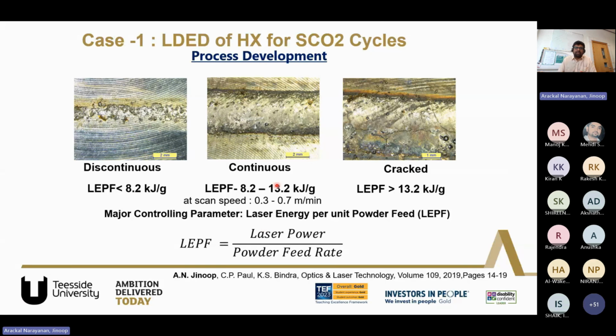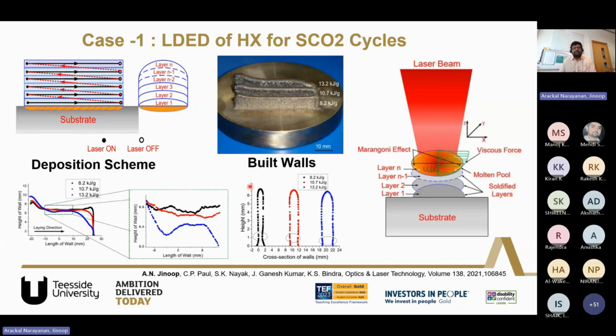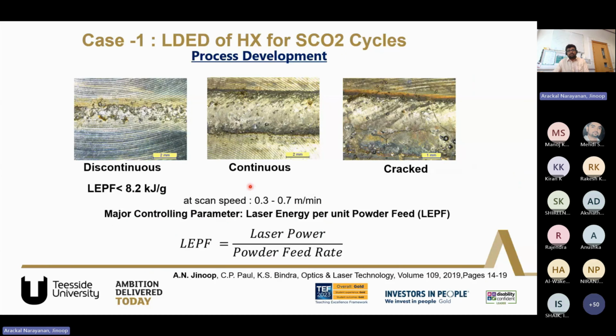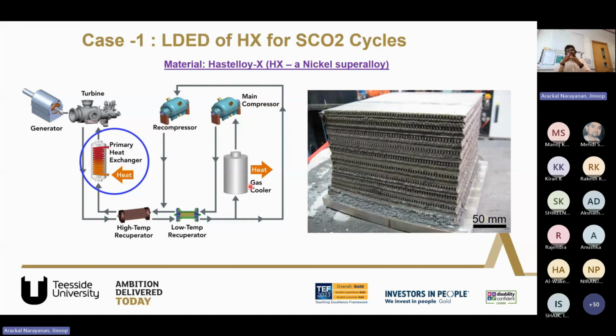And we could identify a range of parameters that could lead to continuous deposition without any cracks. And we correlated it to the energy density that is being used for the process. And then we used it to develop wall. So if you observe this heat exchanger very closely, it has wall structures as well as bulk structures in between. So we did some systematic investigation on wall as well as bulk structures.